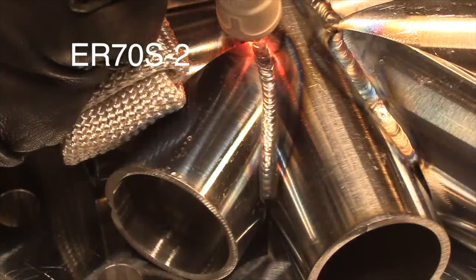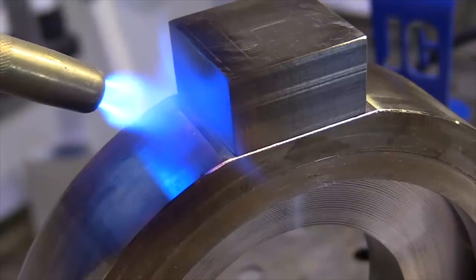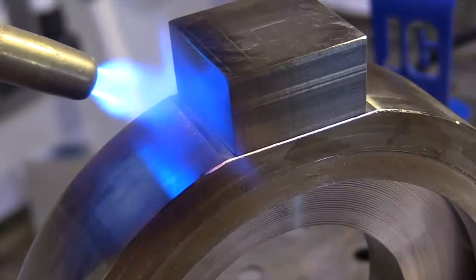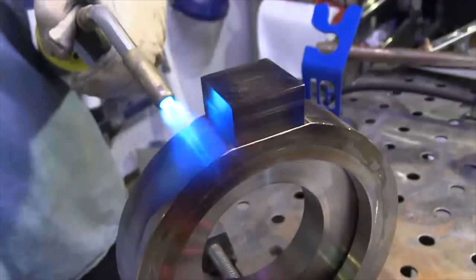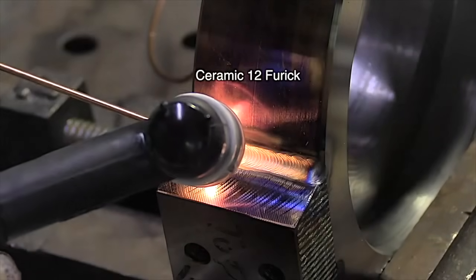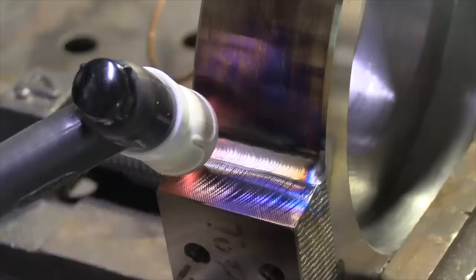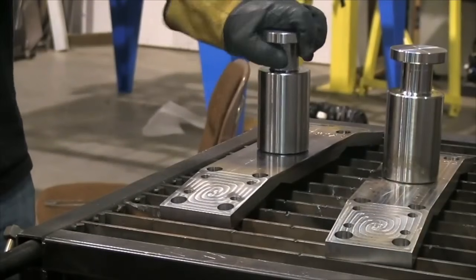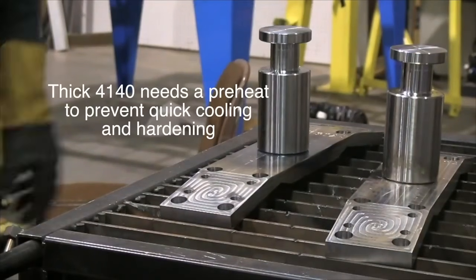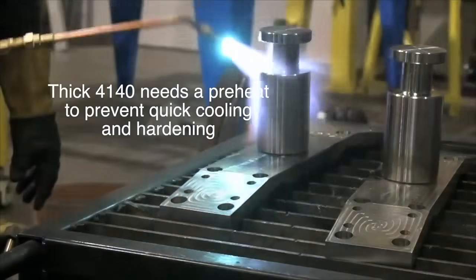Now, here's an example of 0.120 wall thickness chromoly tube. That can be welded without a preheat also. Any thicker than that, you're going to want a preheat. Thicker metals, like this big honking chunk of 4130, definitely require a preheat, and that's usually about 500 degrees Fahrenheit. And that slows the cooling rate down. It's also good to use a welding technique that's rather slow, so that there's no quick cooling going on. And then for higher alloy metals, like a chunk of 4140, like this again, this is actually part of a stand that held an aircraft engine.